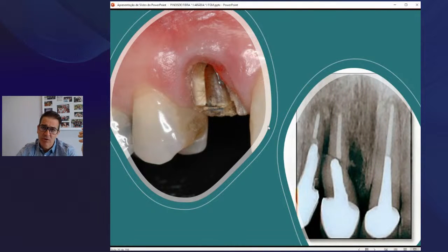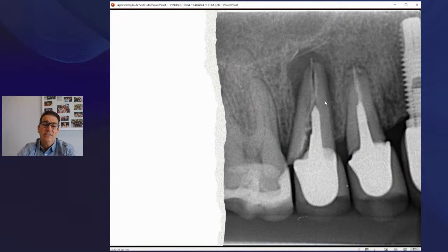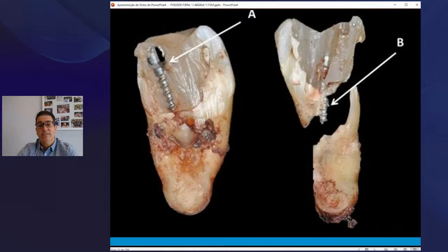Situations like this are not unusual. We see that constantly with the fractures, and sometimes during the process there are perforations because it's a little bit more difficult to take an impression of it. Most dentists don't make them long enough, and we have this kind of situation, which is not unusual, as I said. Look at this: fractures, fractures, and fractures. So metals are very good actually, but prone to a lot of problems. Look at this. This is an extracted tooth caused by a metallic post.